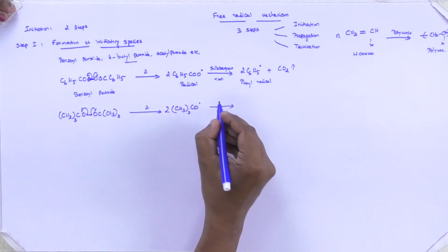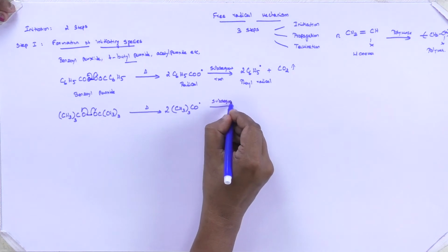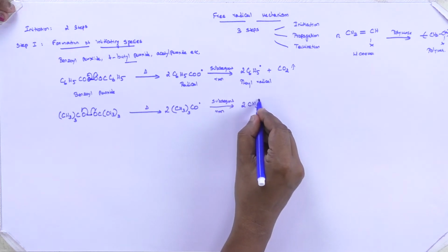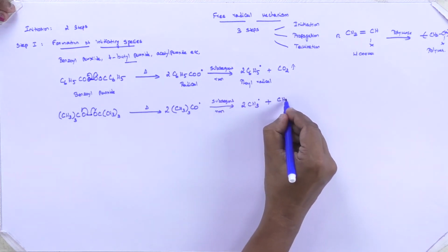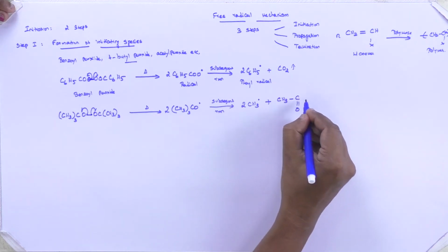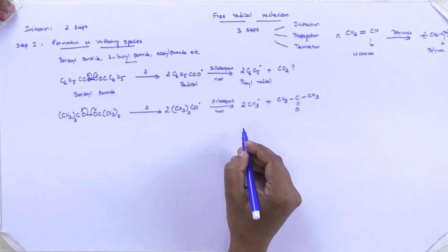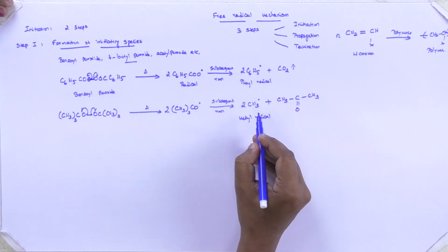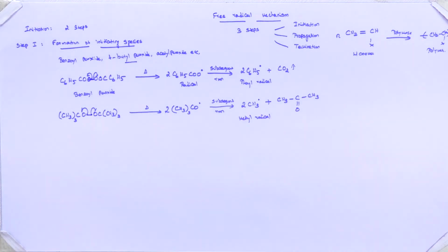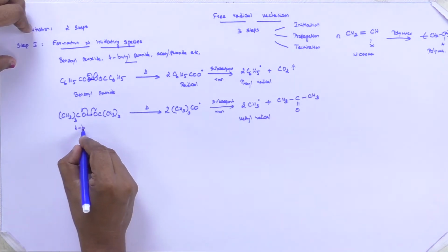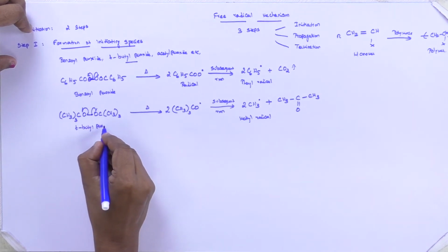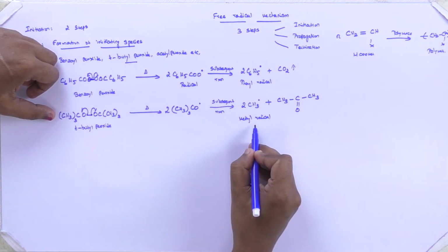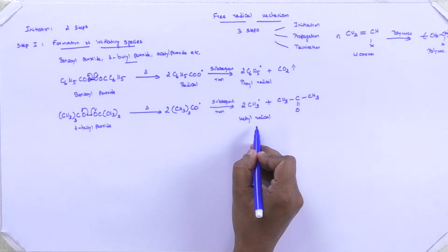The subsequent reaction is that two molecules form methyl radical plus acetone. The initiating species here is the methyl radical, just as the phenyl radical was for benzoyl peroxide. So, tertiary butyl peroxide on heating forms the methyl radical, which is your initiating species.